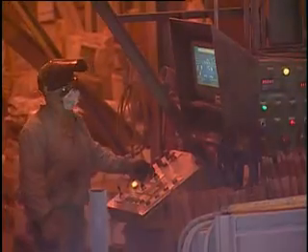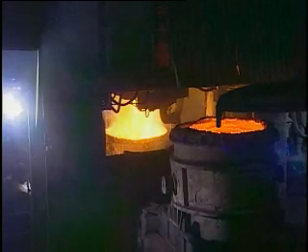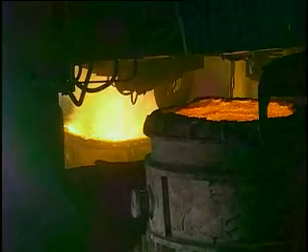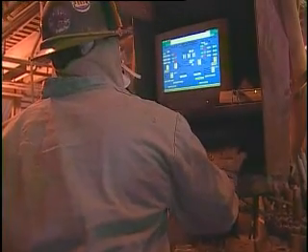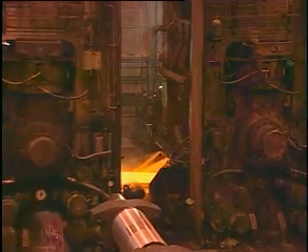The majority of the world's carbon and alloy steel production uses electric arc furnaces. At NUCOR's Berkeley mill, each load consists of 180 tons of recycled scrap and raw iron ore. Once charged into the furnace, an intensely enormous amount of energy, 1,200 volts and 160,000 amps, is added, generating temperatures nearing 3,000 degrees Fahrenheit to melt the charge. Once impurities are removed, carbon and alloys are added to the mix to add tensile quality and produce the required grade of steel. Once it's determined to be perfect, it is molded into sheets of differing thicknesses and widths to meet specific customer orders.